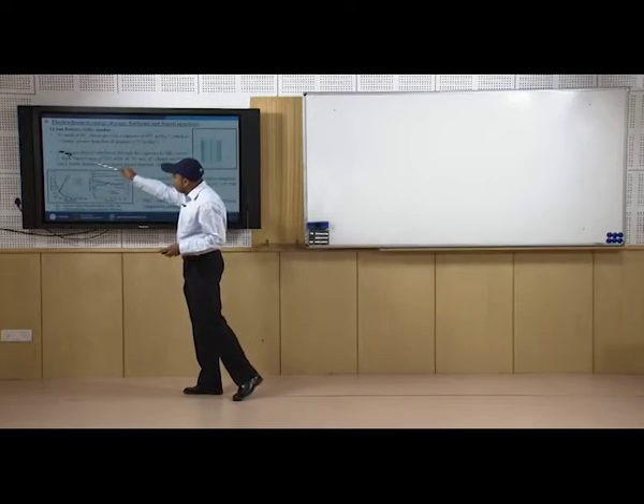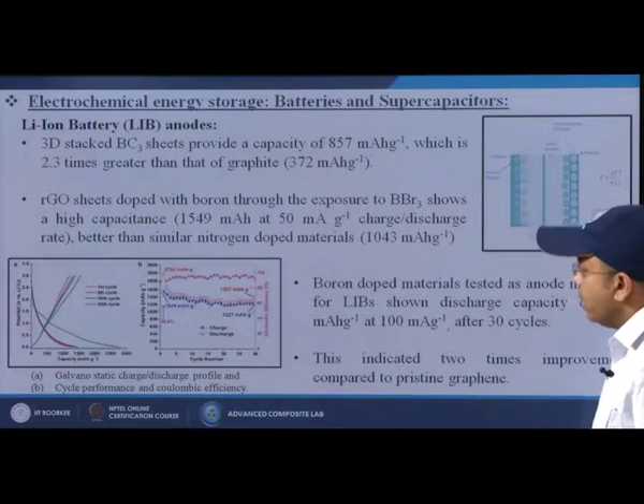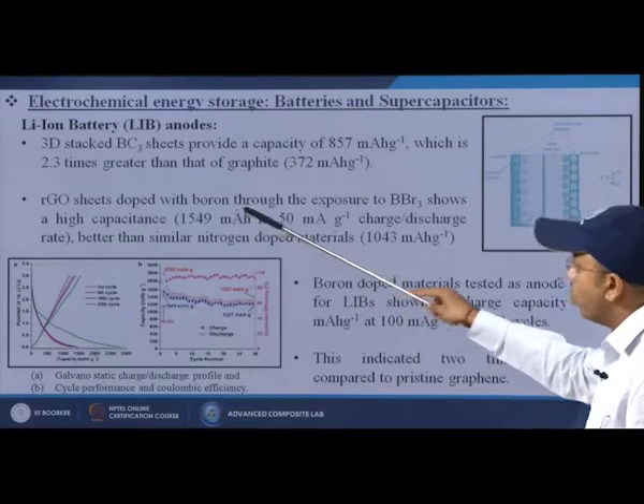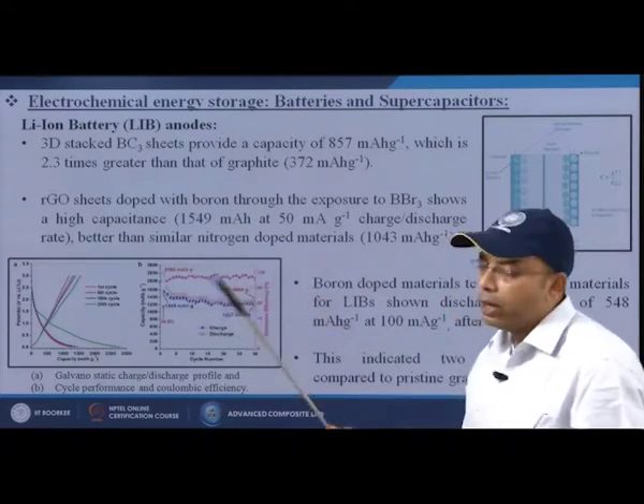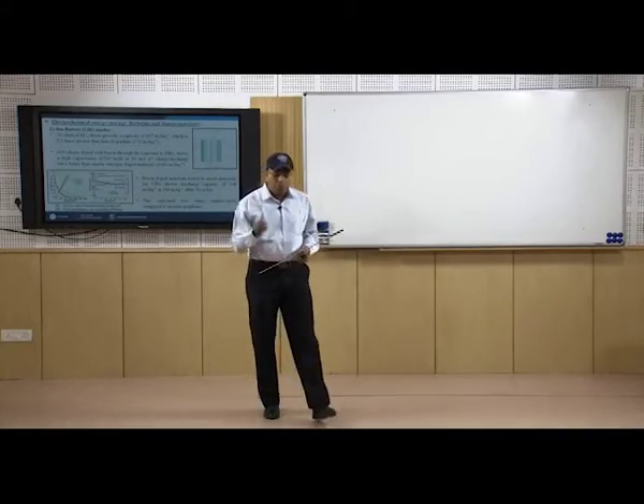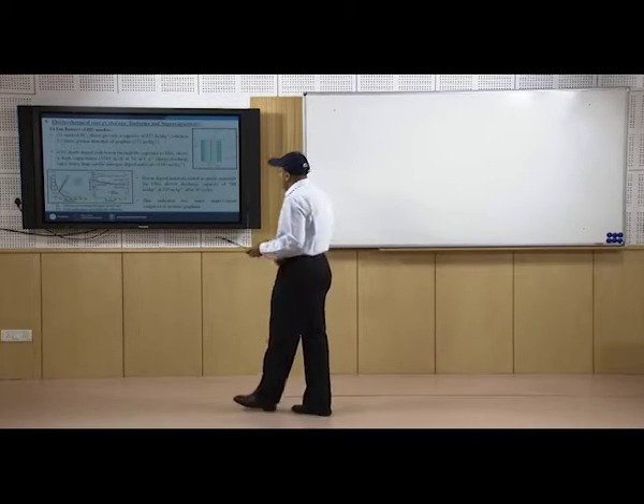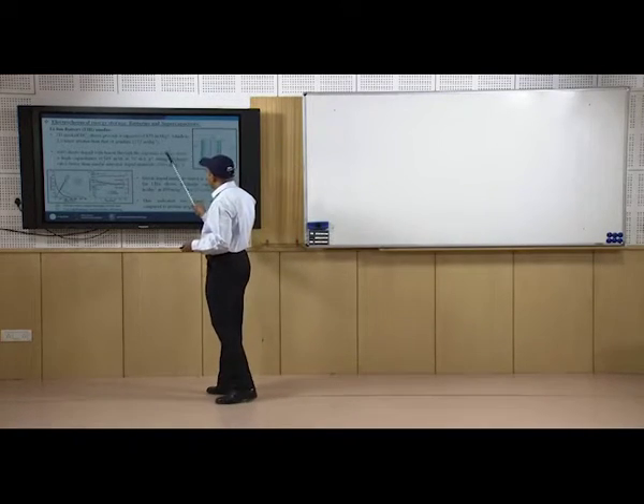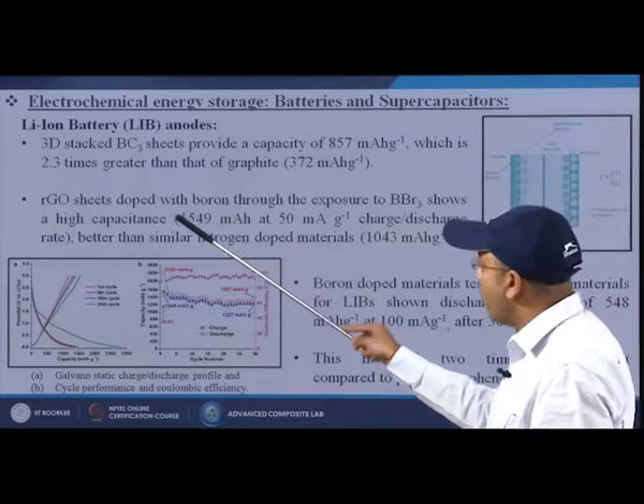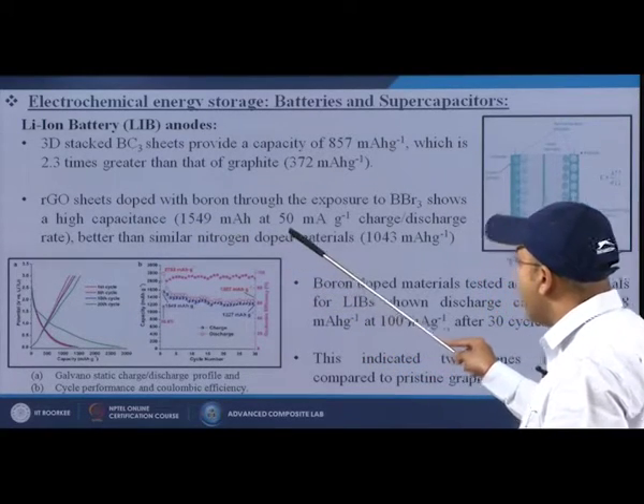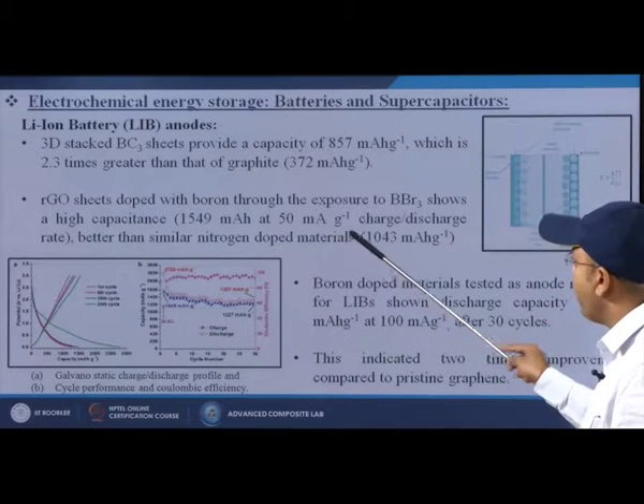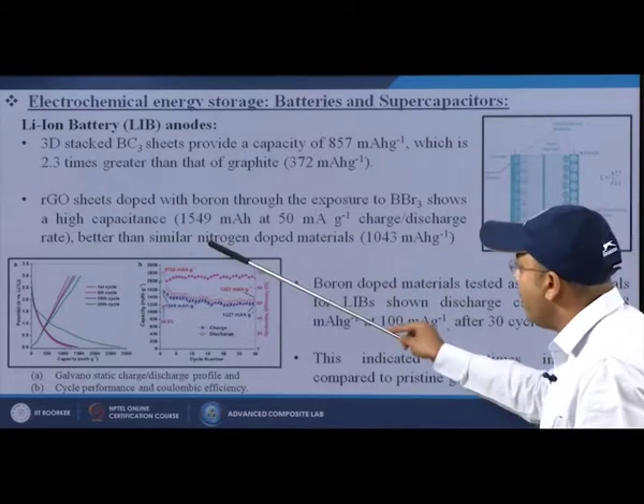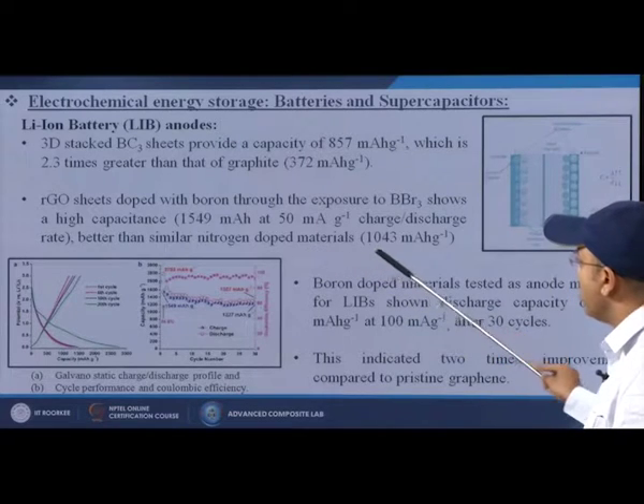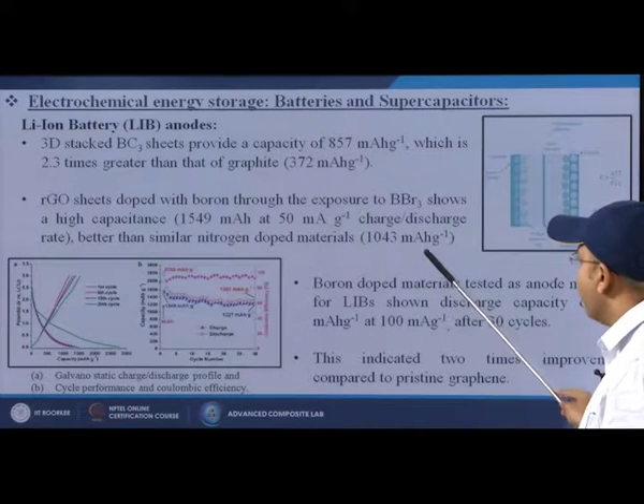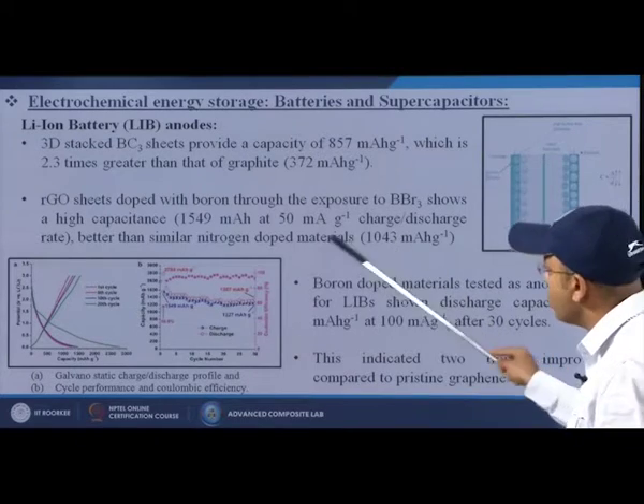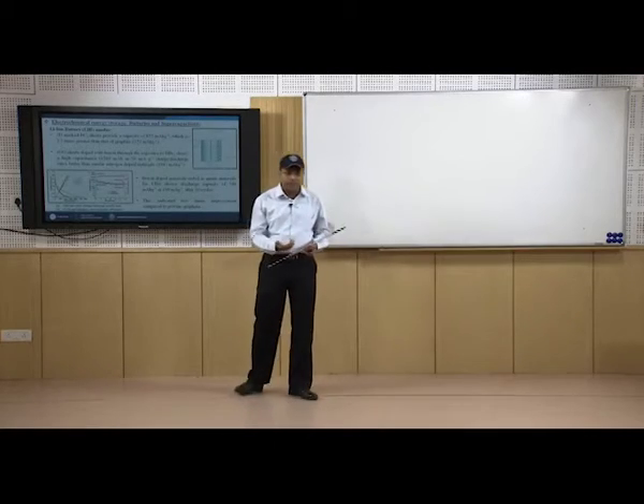Then sometimes we are using reduced graphene oxide, and those sheets are also doped with boron. That means this RGO we are doping with boron, and boron doped RGO material through the exposure of boron bromide shows a high capacity, that is 1549 milliampere hour per gram at 50 milliampere per gram charge discharge rate, better than similar nitrogen doped materials, which are giving only 1043 milliampere hour per gram. So almost the result is 1.5 times better than the previous one.